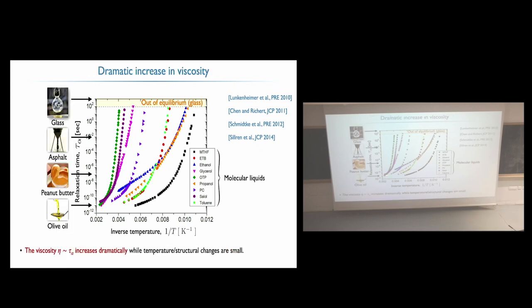To give some ideas about what this means in practice, so this is some work that Misaki has done. On the left, he showed some typical materials that you can all relate to. And this gives some idea about how viscous the liquid is. So typically the viscosity goes like the relaxation time. So here at high temperature, these liquids, all these molecules here, they relax like this olive oil. So it's quite viscous, but still very flowing. After you decrease a bit the temperature, it's already very different. It has the viscosity of peanut butter. I don't know what it is, but Nutella. So the viscosity of Nutella after changing just a little bit the temperature.